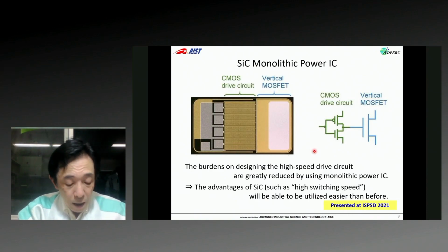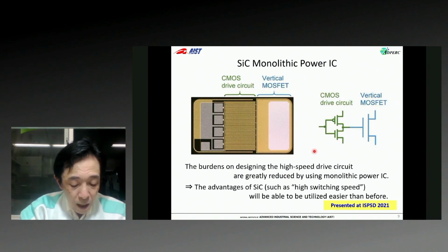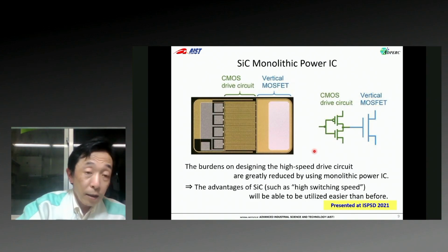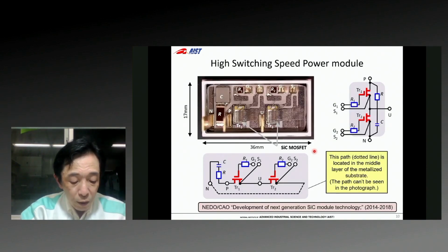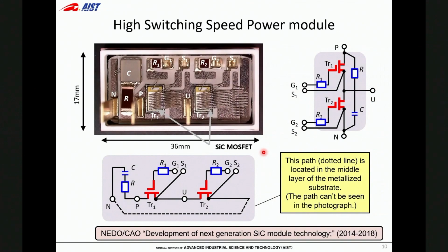By introducing this design, the difficulty in the drive circuit design is greatly reduced, and the advantages of silicon carbide, such as high switching speed, will be able to be utilized more easily than before. Another effort for switching speed improvement in SiC power modules is shown here. The rating of these power modules is 1.2 kilovolt and 100 amps. In the case of high switching speed operation, the switching surge caused by the wire inductance becomes a very big issue.